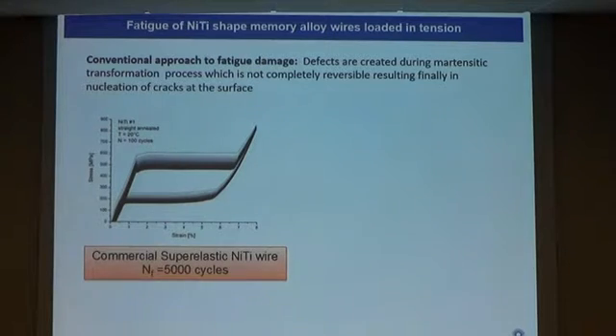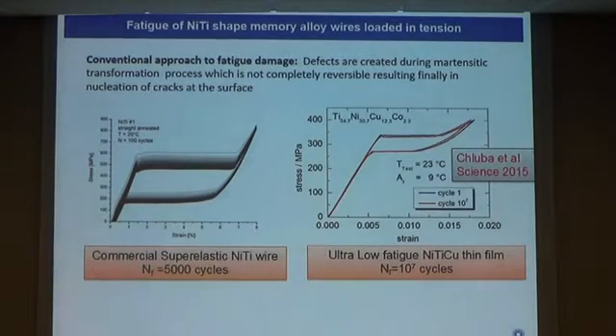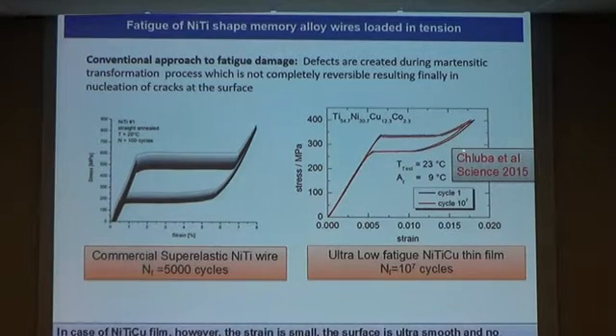Particularly this comparison between the rubber and steel, how we are in between. But in reality, we have here this phase transformation, which should be regarded as a reversible process. In fact, it's not, but theoretically, martensitic transformation is reversible, so we should think about it like a reversible process. And in ideal case, this could be repeated for 200 million times. And it seems it's not possible with wires, but recently it was published with thin films.